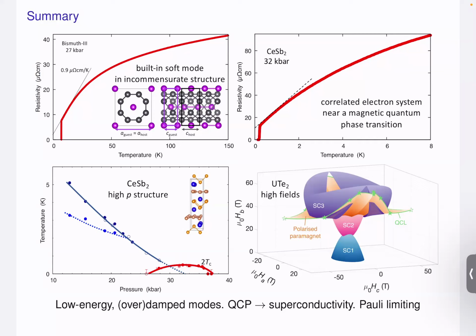But it's not magnetically ordered. So there's some atoms that point up and other atoms that point down. So now the electrons don't move freely. This introduces a strong correlation because they can only hop onto another site if the electrons there are pointing their way. Broadly speaking, this causes the bands to narrow.